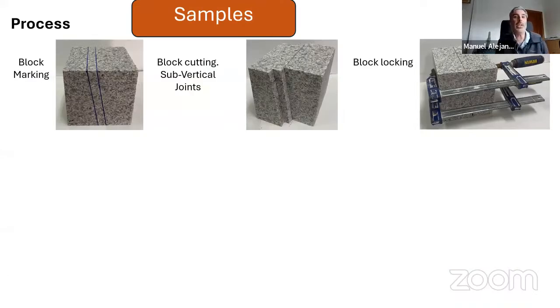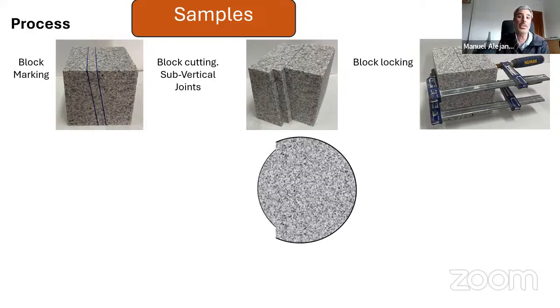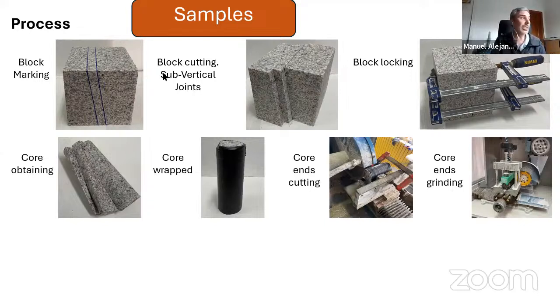So I'm going to explain briefly how the samples were obtained. Here we have the typical block for sample obtaining, and we mark the subvertical joints. Then we cut it using a saw, and then we clamp it together to proceed to drill with a core driller. Why should we perform this first? If we obtain the core first and then we perform the subvertical joint, we obtain a reduction of the diameter of the sample. So this sample will not be usable to obtain results. So we obtain the cores, where here we can see the subvertical joints, and we use electrical tape to hold the core and cut the endings to obtain more or less the length of the final sample.